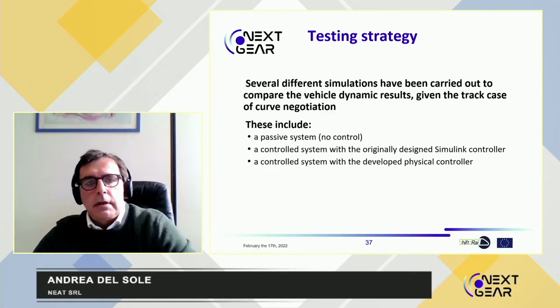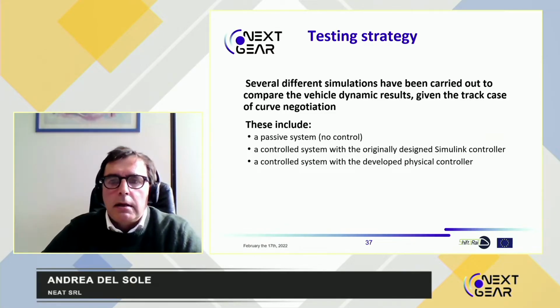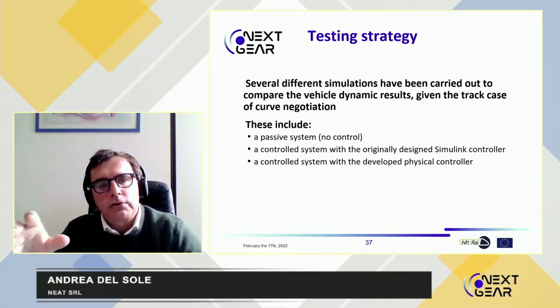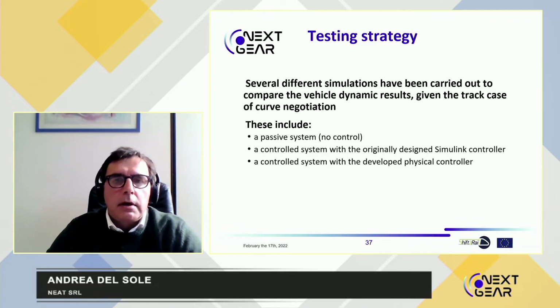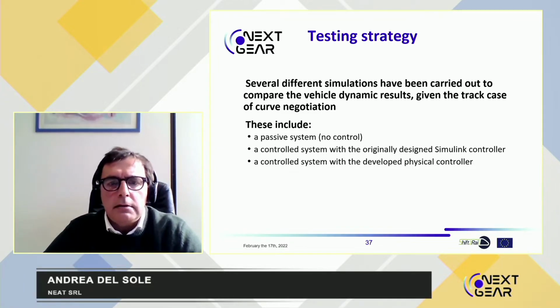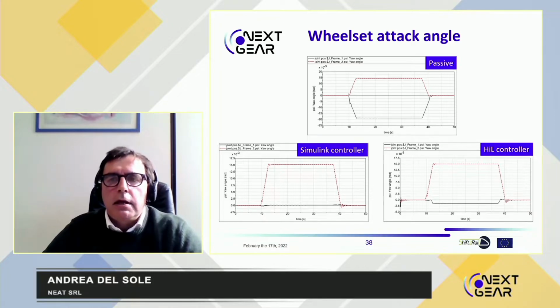The testing strategy we have followed is simply based on 3 different simulations to compare the vehicle dynamic results, given the track case of curve negotiation. So the truck is approaching the curve. In particular, we have compared 3 different systems: a passive one, so one with no control, an active one with the designed Simulink controller, and an active one with the hardware-in-the-loop physical controller in the middle. Those are the results for the wheel set attack angle for the 3 different simulations. It can be seen that both wheel sets of the passive vehicle system have a very large attack angle during the curve negotiation, whereas the controlled leading wheel set in both cases has a much smaller attack angle compared with the passive one. The trailing wheel set without control has almost the same attack angle as the passive one.